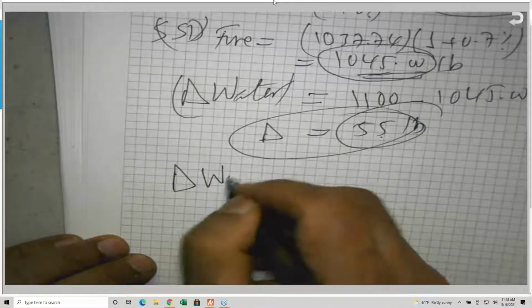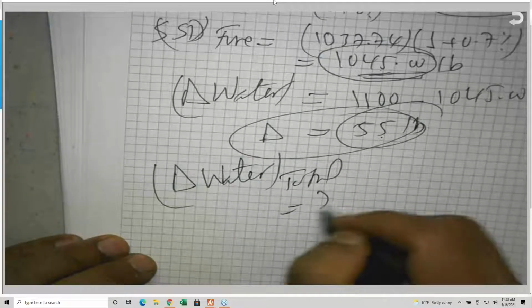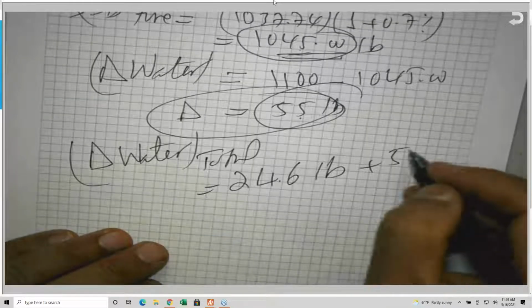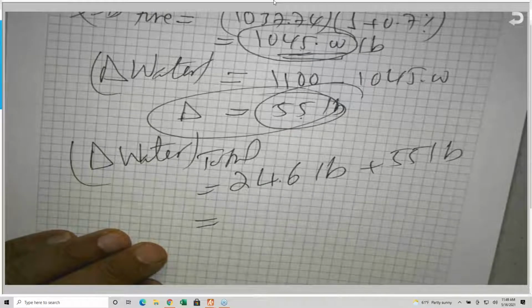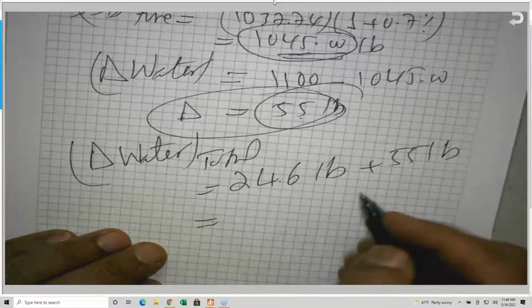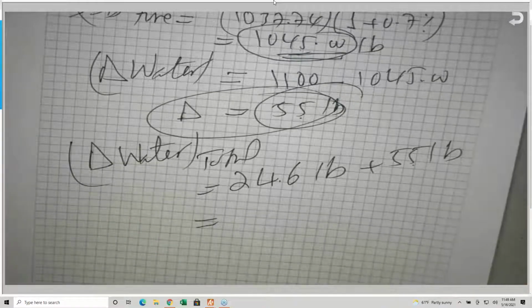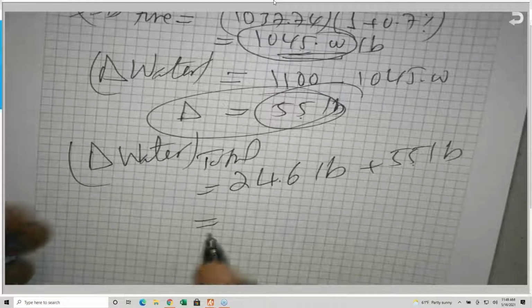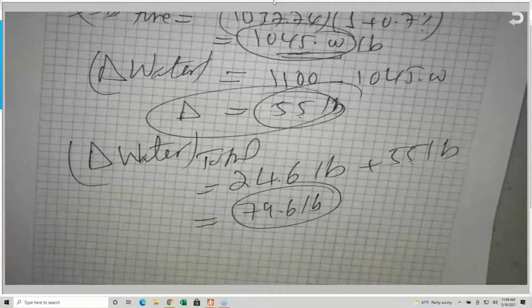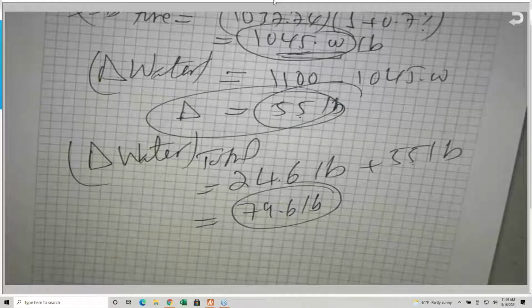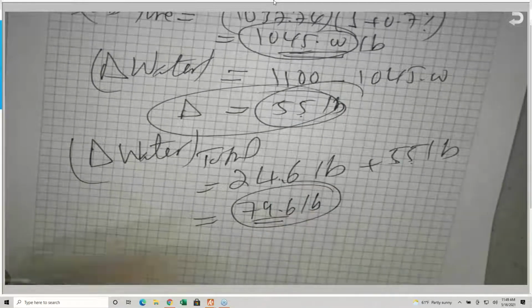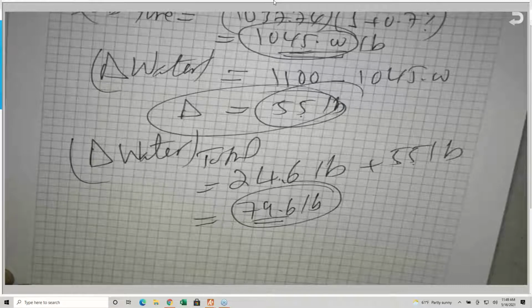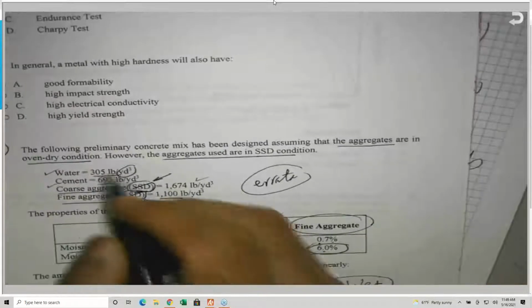So the total water, delta water total, is equal to the 24.6 pounds coming from the coarse plus 55 pounds coming from the fine. Okay, so this will give you what? 24.6 plus 55 is equal to 79.6 pounds. This is the total water that will be extracted from the fine and from the coarse. He added, how much water did he add? He added 305.